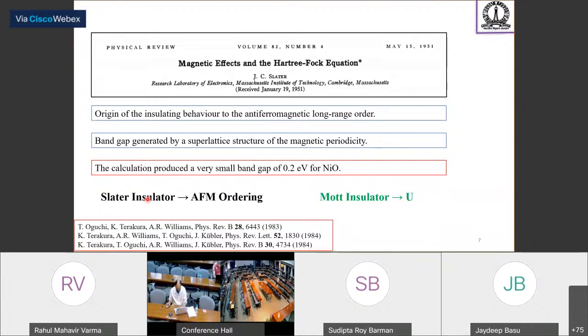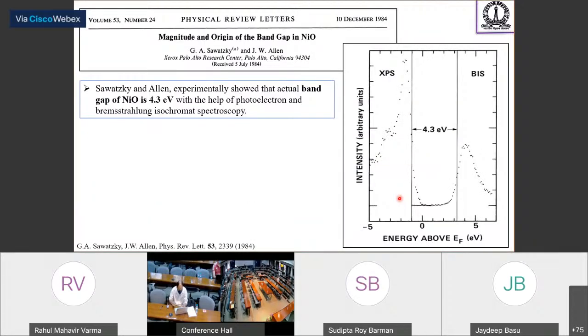But in the case of a Slater insulator, it arises due to the antiferromagnetic alignment. So the Slater insulator must transit to a metal if one goes above the antiferromagnetic transition temperature. But a Mott insulator will remain an insulator even if you go above the transition temperature. So this theory was then falsified by Sawatzky and Allen,